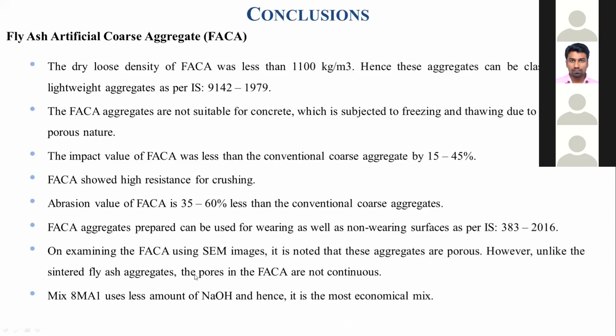My guide explained about the FACA, and the main advantage of the material is that the density of the material is 1100. It comes within the limit of lightweight aggregate. So we are producing a lightweight aggregate, and we were surprised to see how much we can save after that load. FACA aggregates are not suitable for concrete subjected to freezing and thawing. We also did many acid and durability tests, and all passed for FACA aggregates.